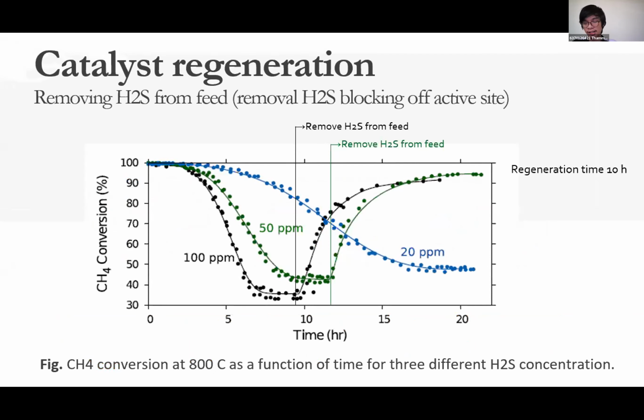After that, we will consider the catalyst regeneration. The first method is removal of hydrogen sulfide from the feed. Since adsorption is a reversible process, surface adsorbed sulfur can be removed by decreasing the hydrogen sulfide content in the feed stream. The figure shows the methane conversion as a function of time for different hydrogen sulfide concentrations. They performed the regeneration experiment for 100 ppm and 50 ppm by removing hydrogen sulfide at 8 and 11 hours respectively. However, full regeneration could not be achieved, and the time required for regeneration is around 10 hours. The catalyst activity lost after the regeneration is mainly due to the chemisorption of hydrogen sulfide on nickel.